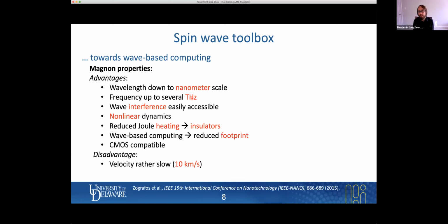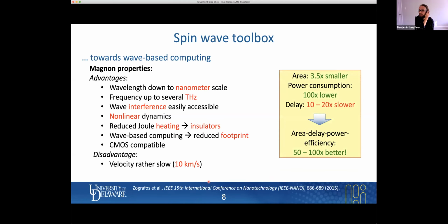Disadvantages are that magnons are rather slow, at 10 kilometers per second. And there are considerations and estimations, which I took from this paper, that tell us that because you can go to wave-based computing concepts, you can make the area of your device 3.5 times smaller, and power consumption can be about 100 times lower. Because of the low velocity, the delay time is 10 to 20 times slower. That's a disadvantage. But nonetheless, this figure of merit, this area-delay-power efficiency, tells us these devices based on CMOS with some additional functionality enabled by spin waves can be 50 to 100 times better. So that's the technological background that I want to give you here.